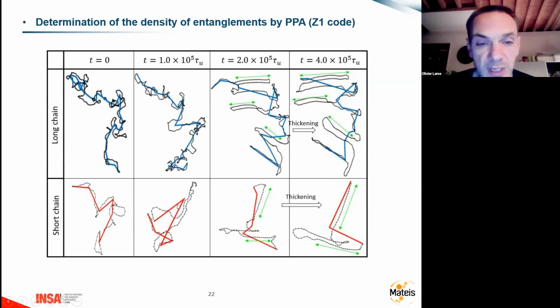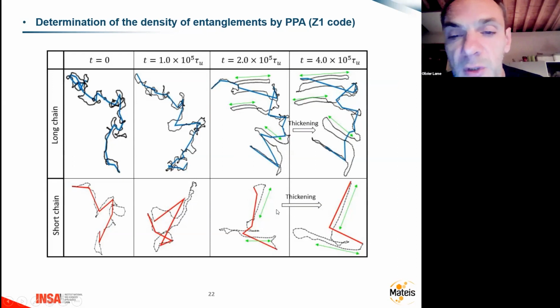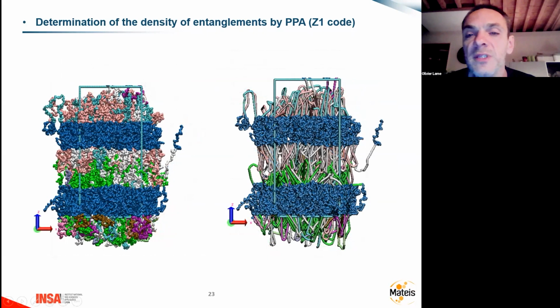For a short chain, it is the same. Okay, and at the end, the primitive path for this chain is very easy. There is only one turn, so let's say one entanglement. Okay, I can discuss this detail after if you wish. Here, for example, for a lamellar structure, which is not the same system, but anyway, this is the same procedure. In between two lamella, you have the system at the beginning, and after this primitive path algorithm, we see stretching in this part, and then we see some turns which correspond to entanglements.